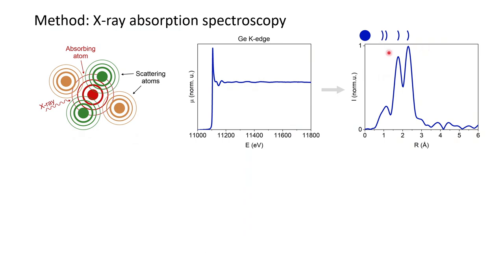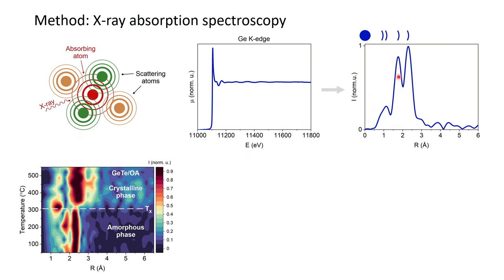And by doing that, we kind of look from the point of view of this single atom of interest, in this case, germanium. And we observe this, so to say, radial distribution function, which has a forest of peaks, and each peak position is proportional to the distance between our germanium atom and other atoms around, like this green or golden one. And the intensity of these peaks tells us something about how many of these atoms we have around our germanium. So we can do that as a function of temperature.